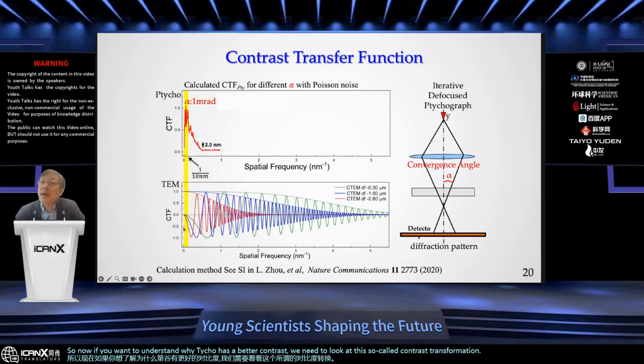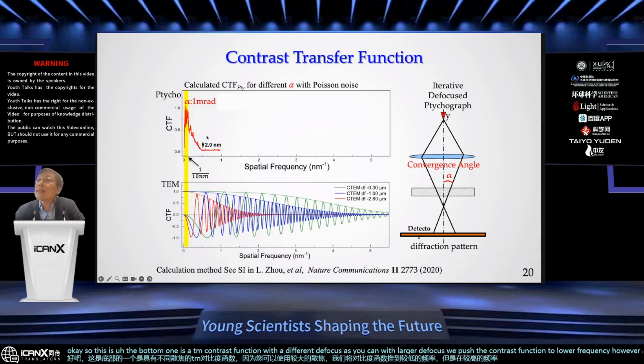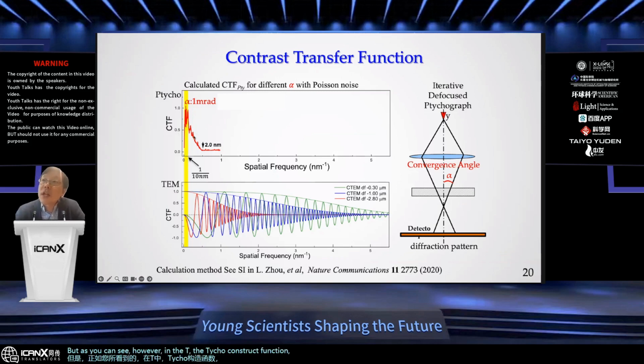Okay, so the bottom one is a TEM contrast function with different defocus. As you can see, with larger defocus, we push the contrast function to lower frequency. However, at higher frequency, the information is scrambled. But as you can see, in the ptychography contrast function, the transfer function is all above zero. There is no intersect or crossover like TEM, which means the ptychography phase imaging does not suffer contrast reversal. Okay, this is the first take-home point.